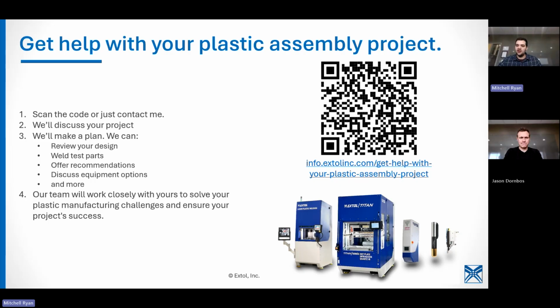And then for vibration and ultrasonic, they both have flash that flakes off in the form of particulate. So if you have a particulate requirement that you need to stay under, that's where you typically use hot plate welding. The other piece is A-surface marking. Both of those tools have the potential to mar the A-surface when you're welding. With vibration welding, you've got specific tooling details that are required, and you can often see the knurling from the vibration tooling on a specific part. With hot plate welding, you wouldn't have that.